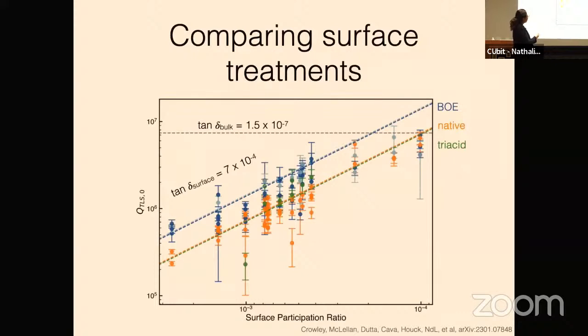And then we can take it a step further and do different types of BOE dips, and also this crazy thing where we boil it in a mixture of nitric, perchloric, and sulfuric acids to try to increase the oxide thickness, and then basically extract out all of these different surface loss tangents. And what we generally find is for our best devices, we have this surface loss tangent that's something like 7 × 10⁻⁴. And then the only way to make all of this data make sense is that there's also something that looks like a bulk substrate loss tangent that's at 1.5 × 10⁻⁷. And this would not be possible unless you really explored this giant parameter space.